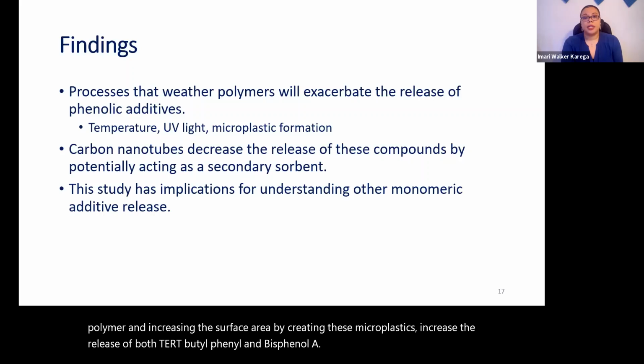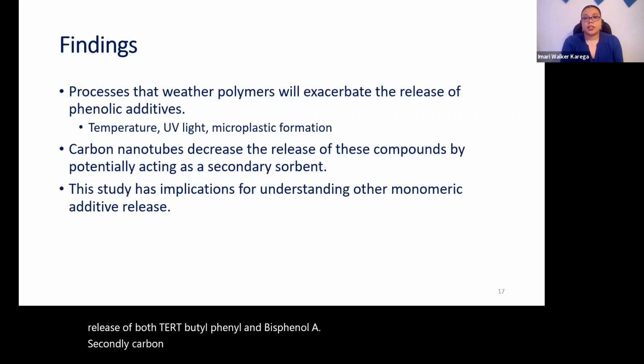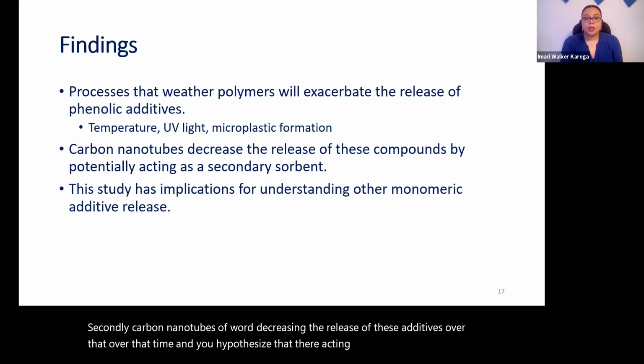Secondly, carbon nanotubes were decreasing the release of these additives over time, and we hypothesize that they're acting as a sorbent for the polymer.